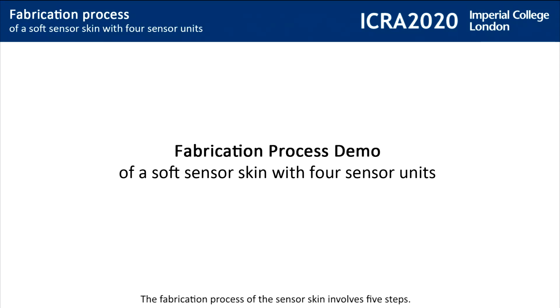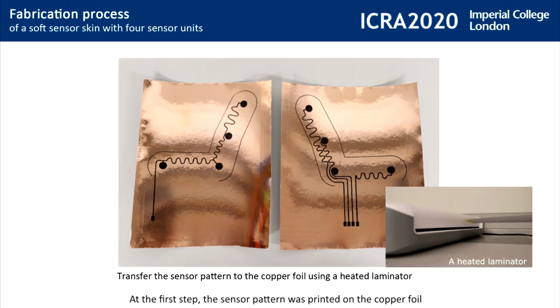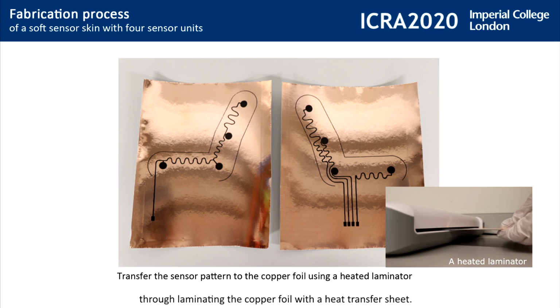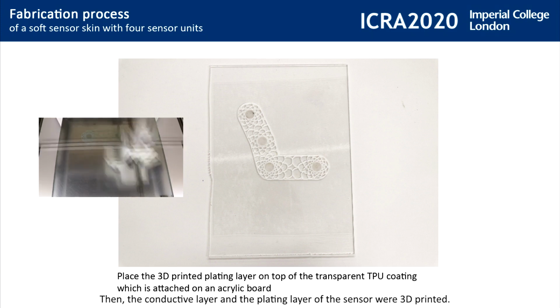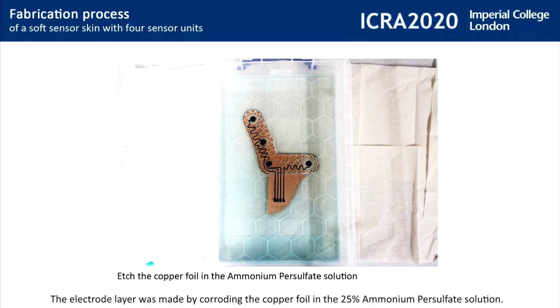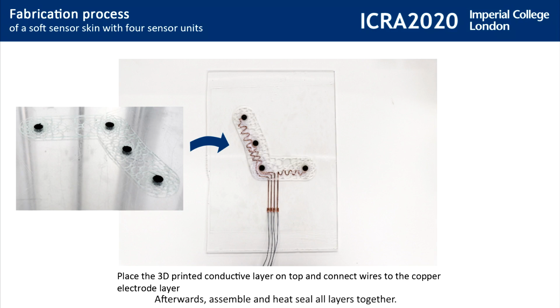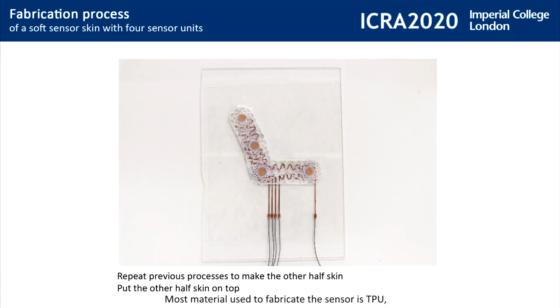The fabrication process of the sensor skin involves 5 steps. At the first step, the sensor pattern was printed on a copper foil through laminating the copper foil with a heat transfer sheet. Then the conductive layer and the packaging layer of the sensor were 3D printed. The electrode layer was made by corroding the copper foil in a 25% ammonium persulfate solution. Afterwards, assemble and heat seal all layers together.